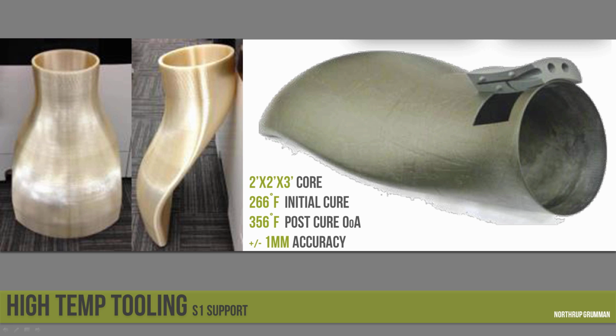Some of the unique things that they did with this is the higher temperature curing, and it's also got a 2-stage cure. Whereas I said the SR30 is good up to 180 degrees Fahrenheit, and the SR100 is good up to 250 degrees Fahrenheit, the S1 can go up to about 350. The two soluble materials can actually go through a 2-stage curing process as well. So the initial curing process might be up to 180 or 250. That's going to cure the composite enough so that if you go to a second curing stage that's higher temperature, the composite's not going to change shape even though you might lose some of the support. So that's totally possible. And that's kind of what they did here.